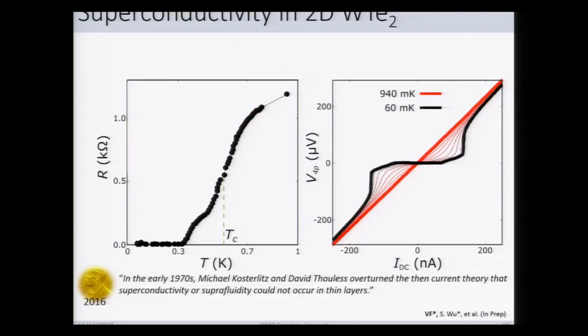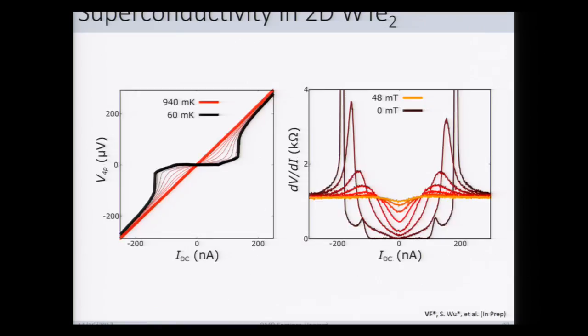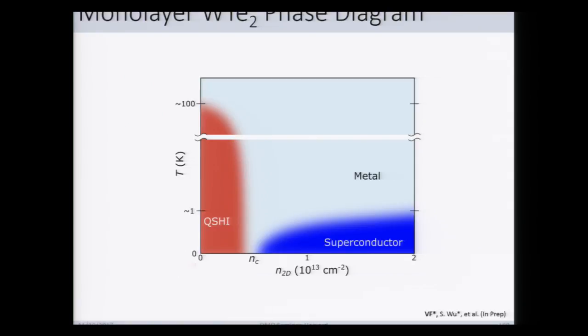You see this little shoulder here that may be due to an inhomogeneity in the sample that may complicate our analysis. So we're not presuming anything necessarily to happen at this critical density. But I'll note, for example, that we have another device where the critical density appears to be slightly lower. So this may not be a universal value. We may not have found the universal value for this density yet. So we're trying not to be too presumptuous about what happens here.